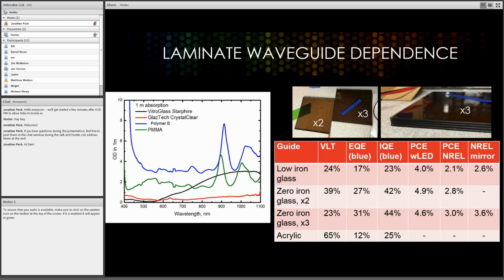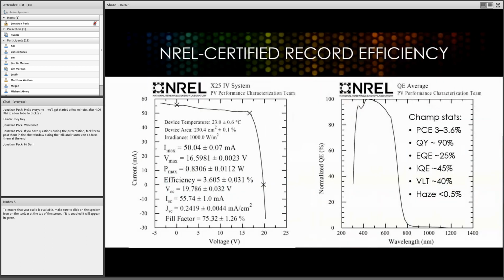And then that translates into, for the best case, our current certified record of around 3%. And then if you add a mirror, which sort of simulates having a low E coating, around 3.6%, which is not published yet, but is the record efficiency for a solar window to the best of our knowledge. And here's some pictures of the NREL certification.